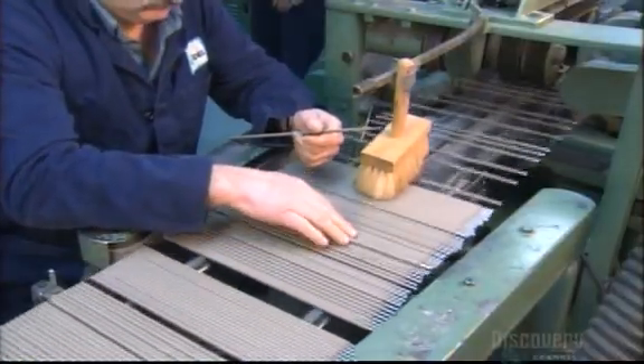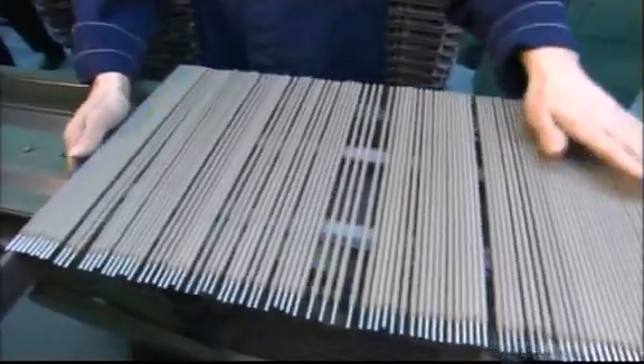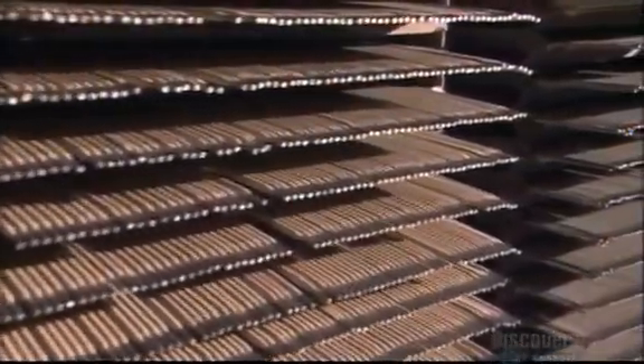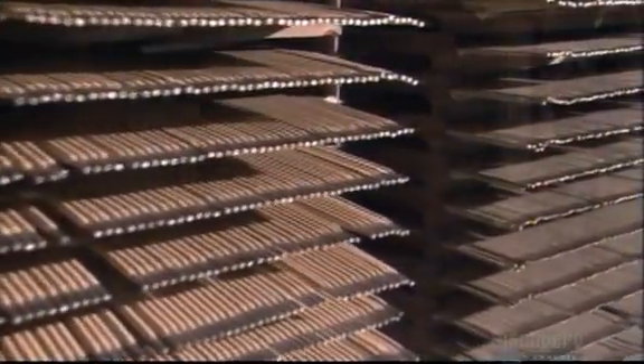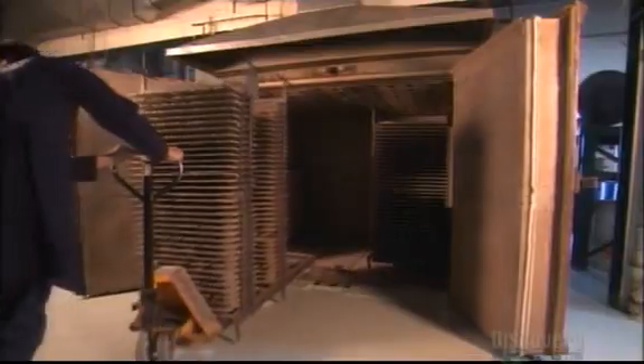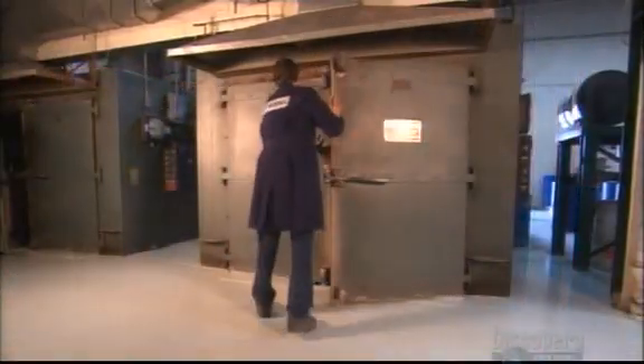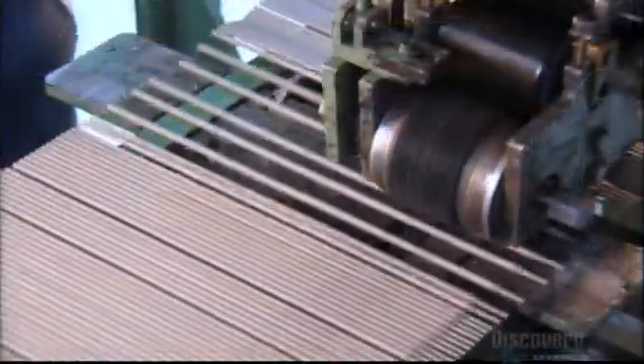A worker now checks for uneven coating and to see if the wire's well centered. The coating dries at room temperature for up to 72 hours. To cure the coating, workers put the electrodes in an oven heated to 485 degrees Celsius for up to 5 hours. Once they've cooled, the electrodes head into a printing press.